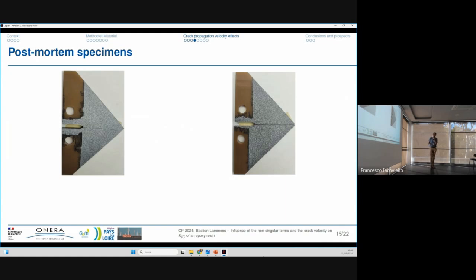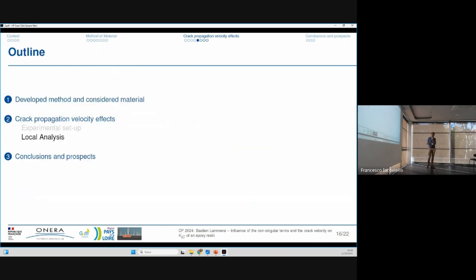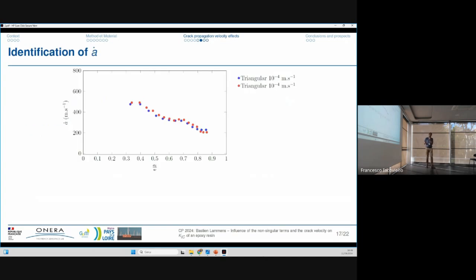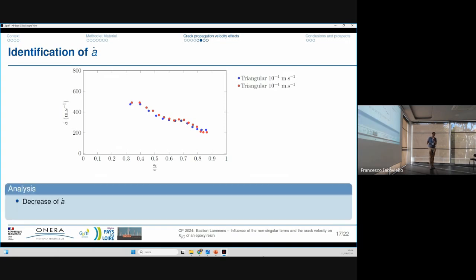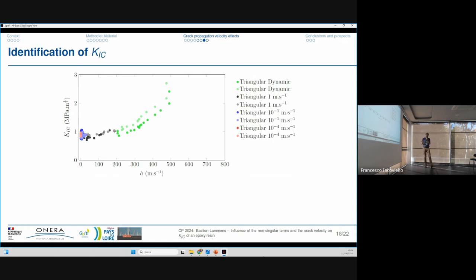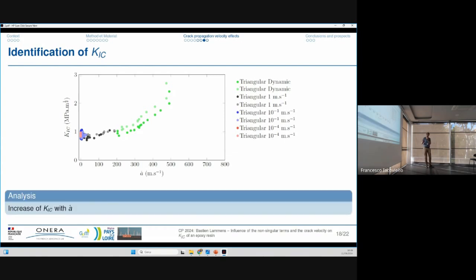So this is the result of the fracture experiments, and we have stable crack propagation. Now, if we look at the local analysis, we can see here the crack propagation velocity decreases with the crack propagation, which can be explained by the stored energy at the crack tip, which decreased during the crack propagation. But we have crack propagation speeds between 200 and 500 meters per second. It was as expected. So now we used all the fracture specimens that I did during my PhD to show the evolution of the critical stress intensity factor with the crack velocity. So we can see we have an increase of the stress intensity factor with the crack velocity.